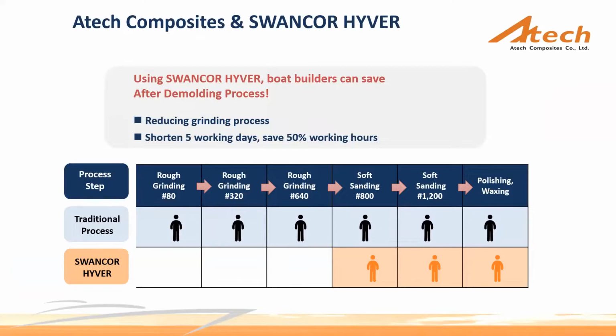And these builders need to do surface fairing work to eliminate the bad surface. The main process to eliminate the pattern is always rough grinding the gel coat surface. After grinding the gel coat, if these builders find that the gel coat coverage is not enough, they have to respray the gel coat. And after respraying, they also need to do rough grinding and soft sanding work.